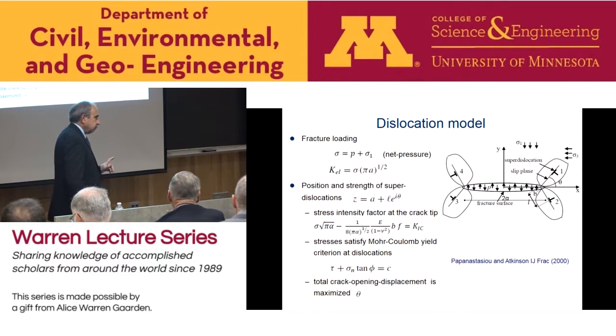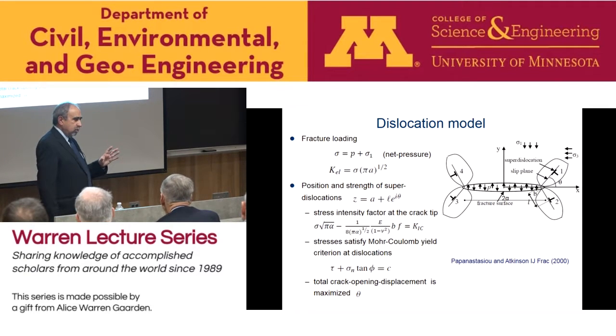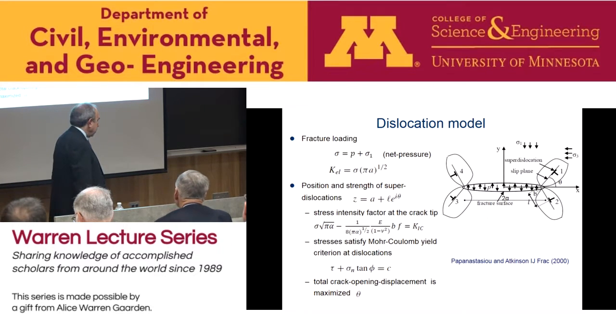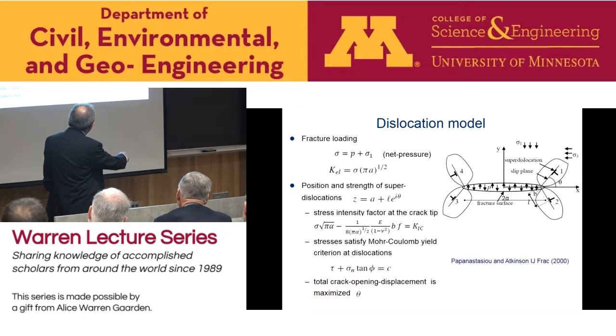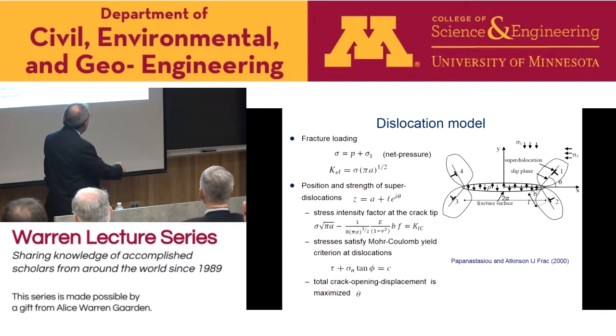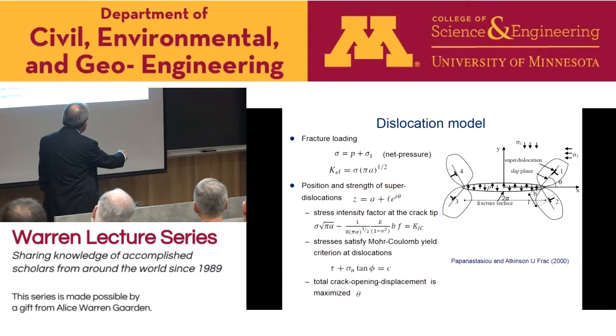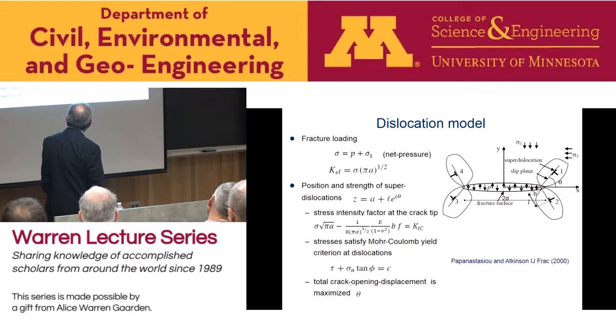Now, we did also some analytical work. Analytical work is always useful to identify the critical parameters, especially the combination of the critical parameters. In this relatively simple model, we have again the fracture here and the plastic zones around the fracture tip as the orange shape I showed before. We say that we will replace these plastic zones with a pair of dislocations. The distributed plasticity will be replaced by this pair of superdislocations. This is what we called, again borrowing from work in metals, and I did this work with Colin Atkinson.